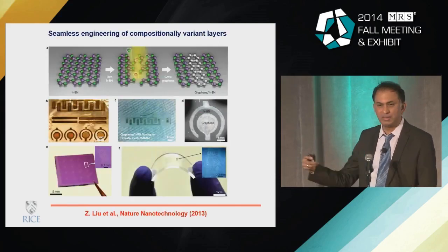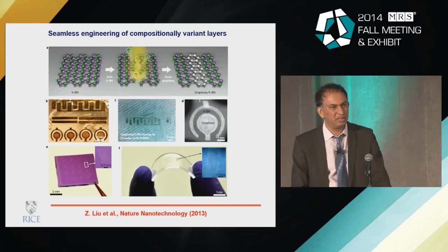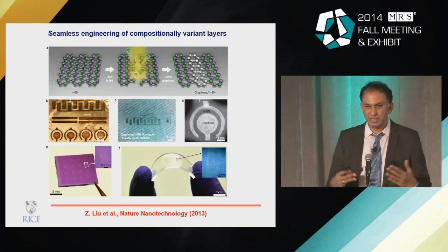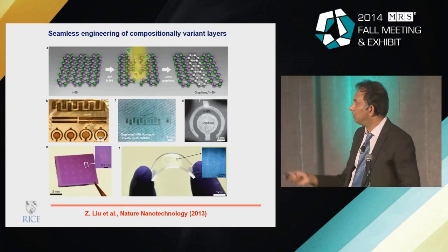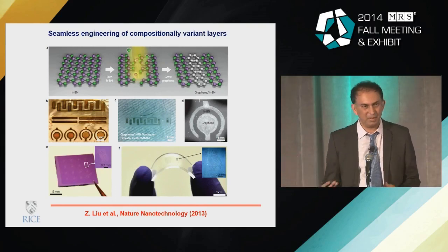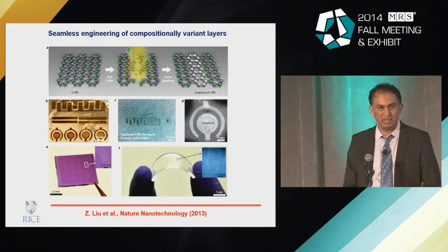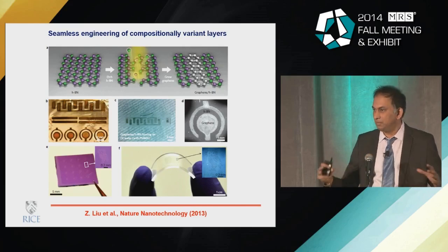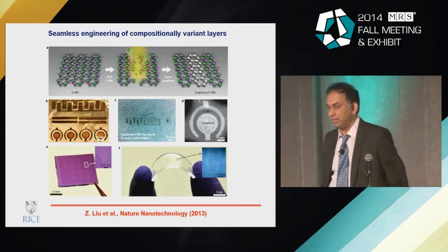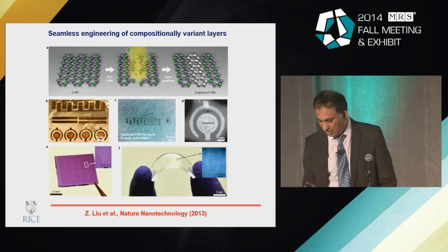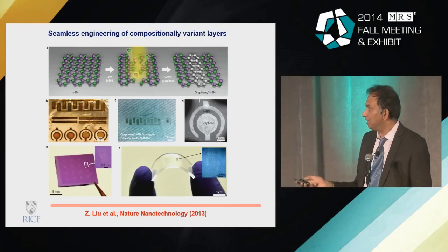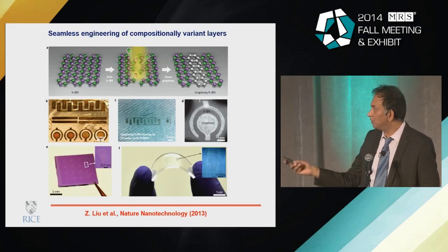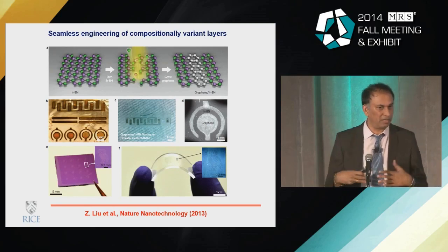And following that idea, we have been in recent years trying to design different domains of different sizes and shapes within these atomic layer matrices. So you can start with boron nitride, for example, etch away some of it, and regrow the graphene in that region, and essentially build up any kind of circuit or domain that you need in terms of shape and size, and basically stay within this atomic layer. And the good thing is that these interfaces are quite strong and continuous.